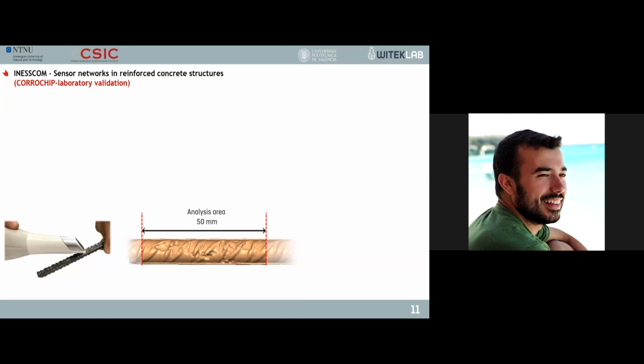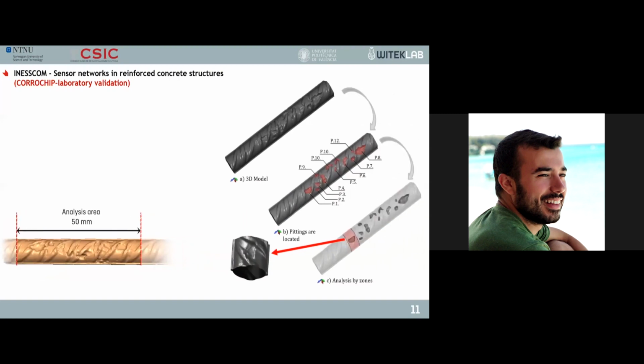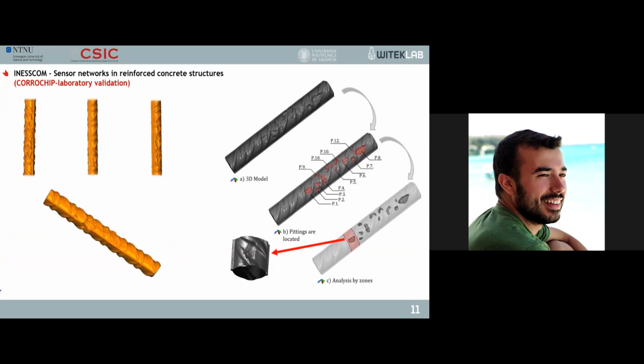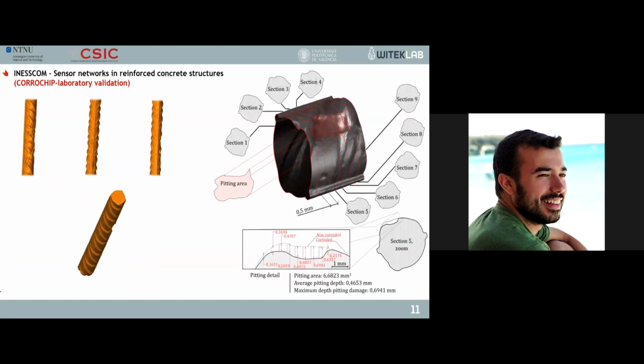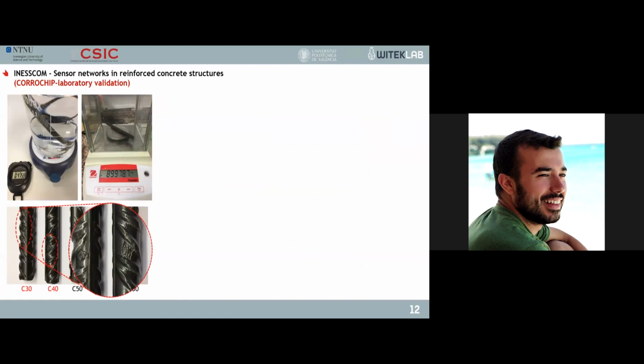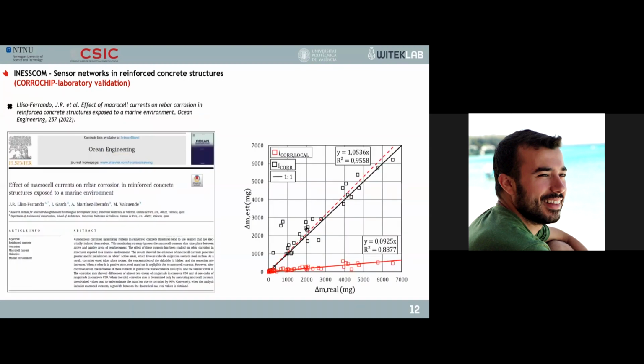Validation of this type of study is usually carried out using the gravimetric technique. However, the authors of this study also decided to use a very precise scanner to identify even the pits in detail. As you can see, the detailed analysis of the pits is incredible. This analysis and the gravimetric study were compared with the results obtained by estimations using the Corrochip monitoring data. As can be seen from the graph, the deviation is minimal, close to 5%, the black line. On the other hand, when using methods that do not consider macrocell currents, the deviation committed is more than 90%, represented by the continuous red line. As I said earlier, this work is accessible and can be studied in more detail, but in summary, this study proved the accuracy and reliability of the monitoring system and the measurement method.